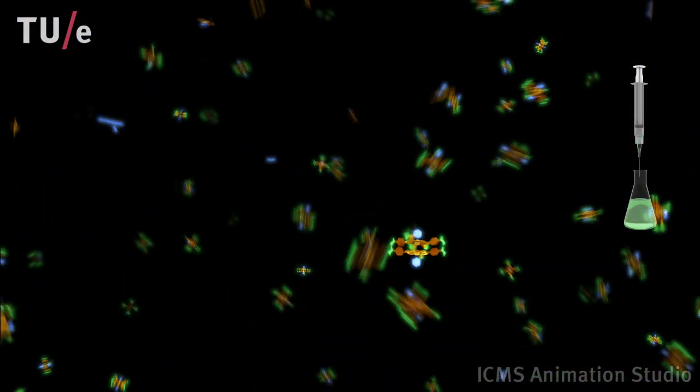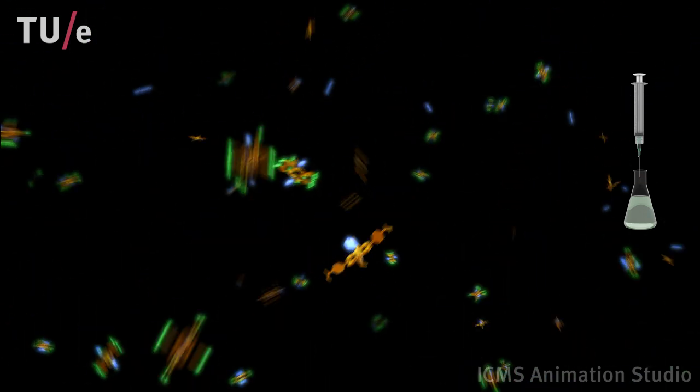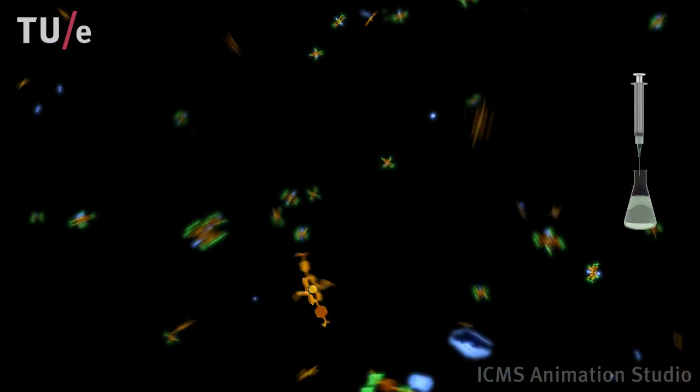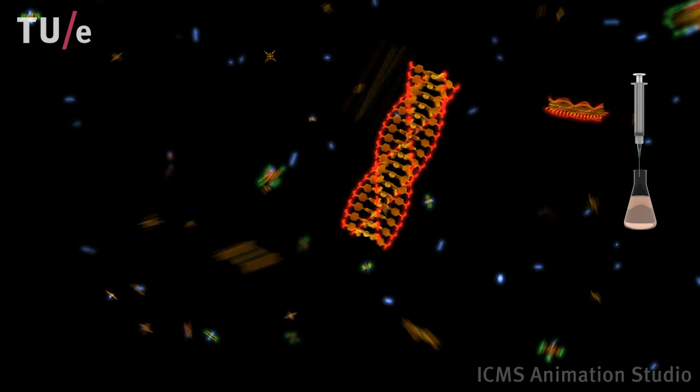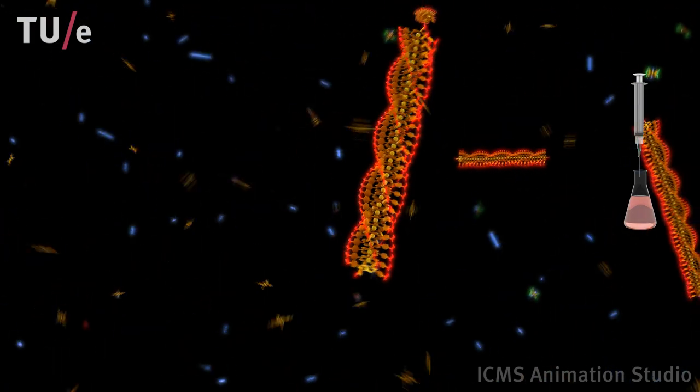Upon the addition of solvent to the fully depolymerized state, the stability of hydrogen bonding inside porphyrin stacks increases relative to the formation of dimers. As a result, decomplexation allows the cofacial arrangement of porphyrin monomers inside stacks while dimers are sacrificed. Due to the shift of coupled equilibria, a dilution-induced self-assembly is observed.